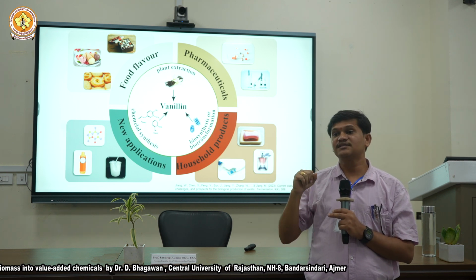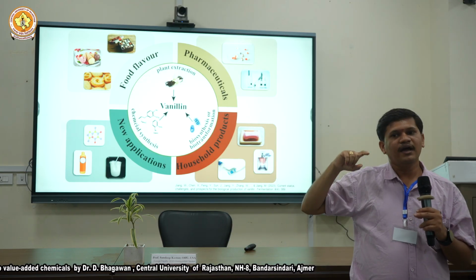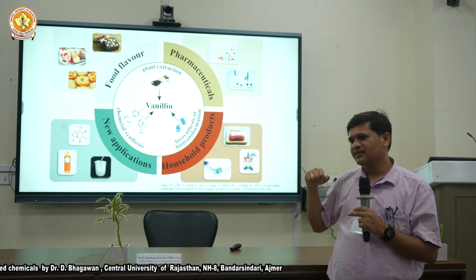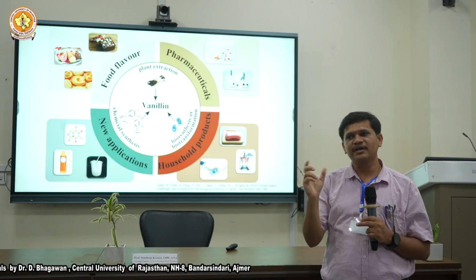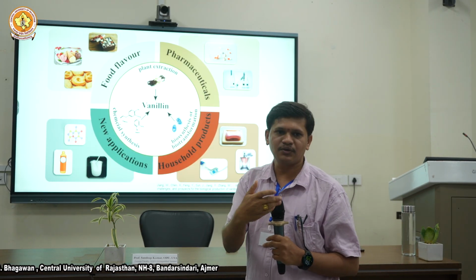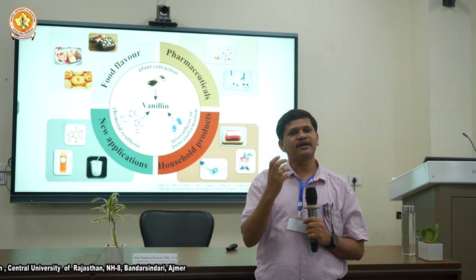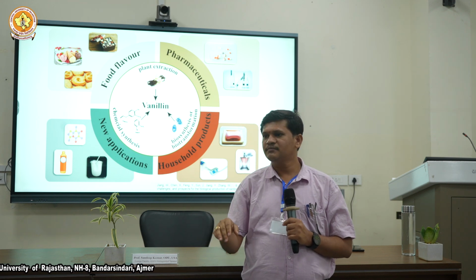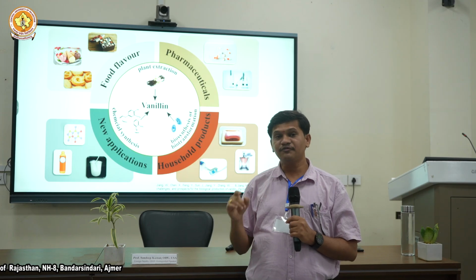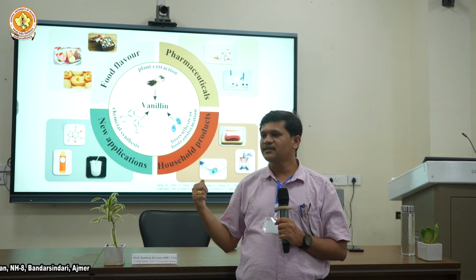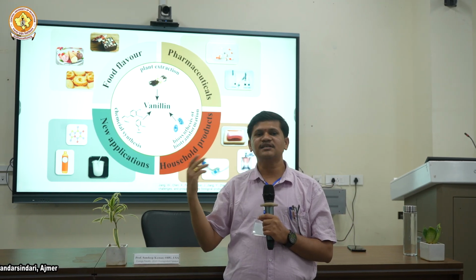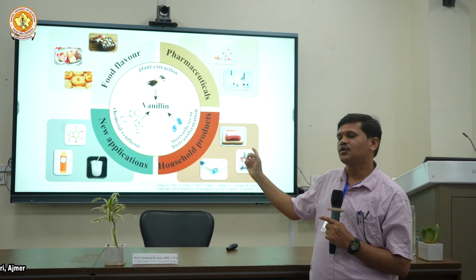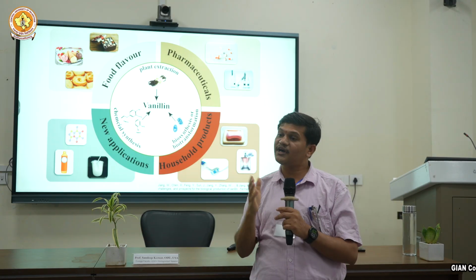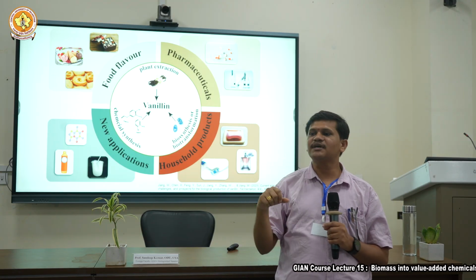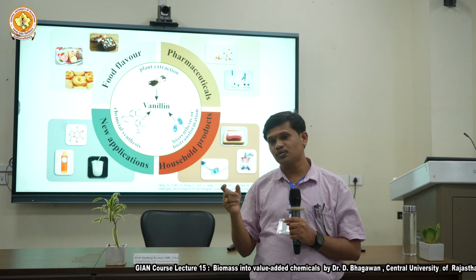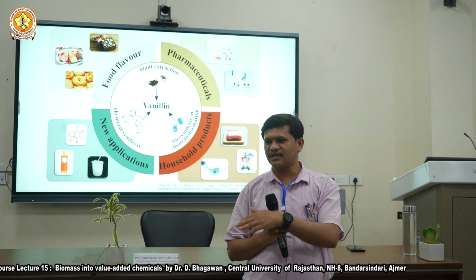Suppose, as I said, the superoxide radical is helping us. First suppose the superoxide radical is not participating in the reaction and the only reactive species is the OH radical. Then how can we control it? During the early stage, as I mentioned, if we use an aqueous medium and allow air into our medium, then oxygen species will exist in our system. If you create an anoxic system and use an organic solvent, without oxygen, then you can reduce the generation of superoxide and have only hydroxyl radical in your system. That way also we can control it. But in this reaction, we have proven that superoxide is acting as a selective radical species. That way also we can control the conversion rate and enhance the yield.